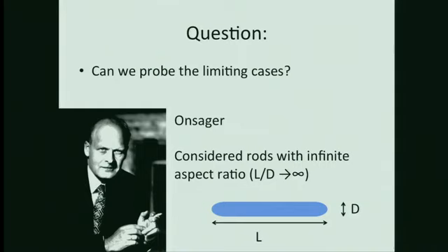And then the paper is a masterpiece because he had to first make it plausible that it was excluded volume interactions, and then, once he had shown that the interactions behaved like effectively hardcore repulsion, he went on to show that that was enough to get an isotropic-nematic transition. The important thing in Onsager's model, he is smiling at you, is that he considered rod-like particles with a length L and a diameter D, and then focused on the limit L over D going to infinity.